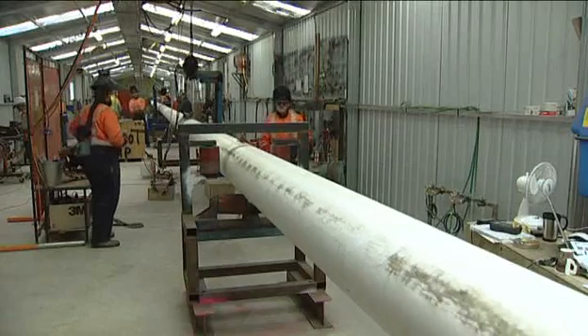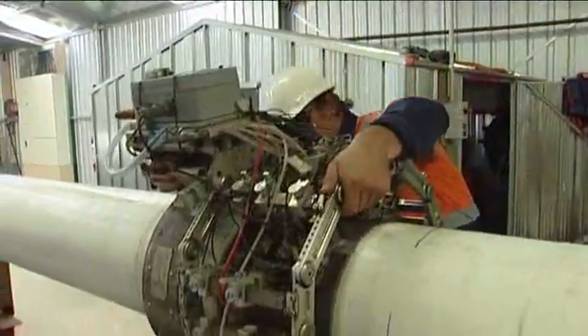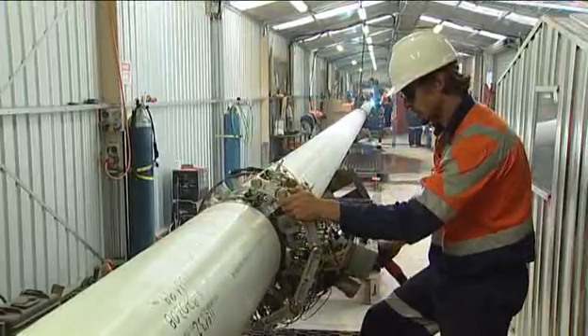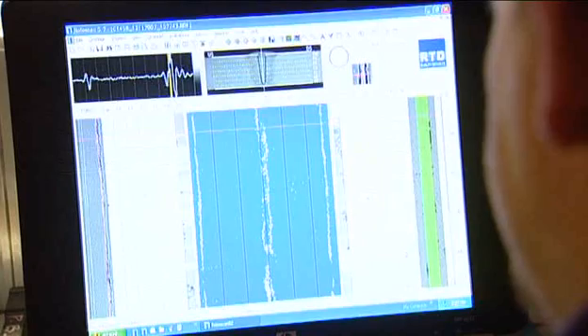From the welding stations the pipe was moved onto the non-destructive examination area. As the pipe was to be subjected to strain as part of the reeling and pipe lay process, the welds were inspected using state-of-the-art automated ultrasonic testing (AUT). The acceptance criteria for the inspection was defined by a project-specific engineering critical assessment (ECA), carried out by Technip, and was particularly stringent.